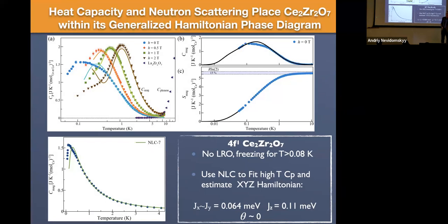So what we can do is a sophisticated analysis of everything else that we've got. And everything else that we've got are thermodynamic measurements, so heat capacity, magnetic susceptibility, and those diffuse neutron scattering patterns. Here's our low temperature neutron scattering, our low temperature heat capacity. This is at sufficiently low temperatures that it's all due to those pseudo-spin degrees of freedom on the cerium site.